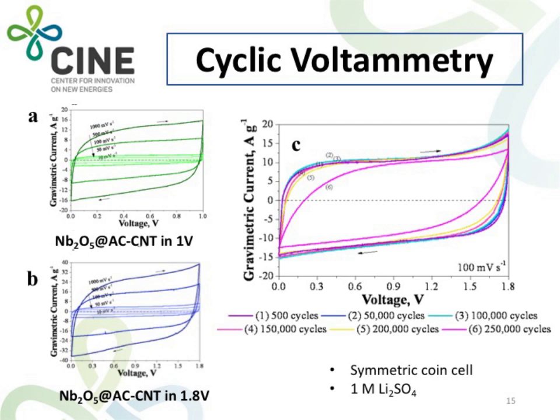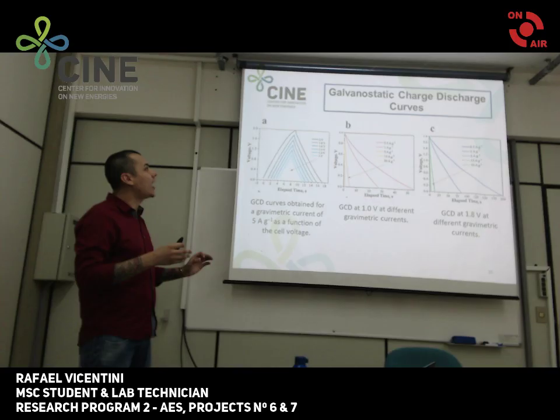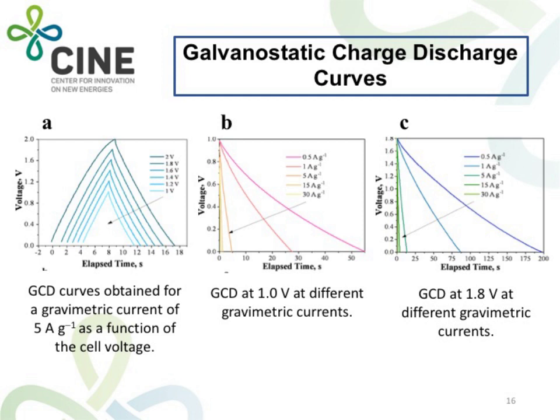Next, we have the galvanostatic charge and discharge curves, or GCD curves. In figure A, we can see the GCD curves as a function of the cell voltage, and figures B and C show the GCD at 1 volt and at 1.8 volts. In both cases, we have used different gravimetric currents, and we have an expected shape for GCD.